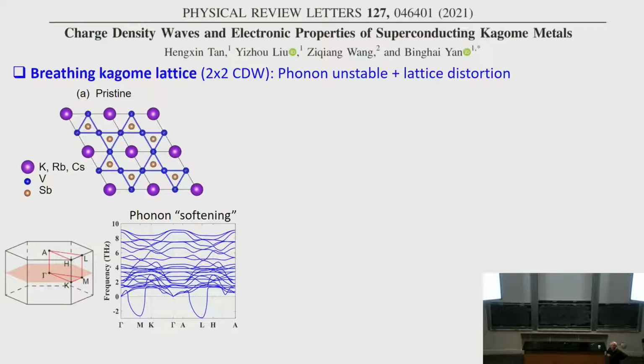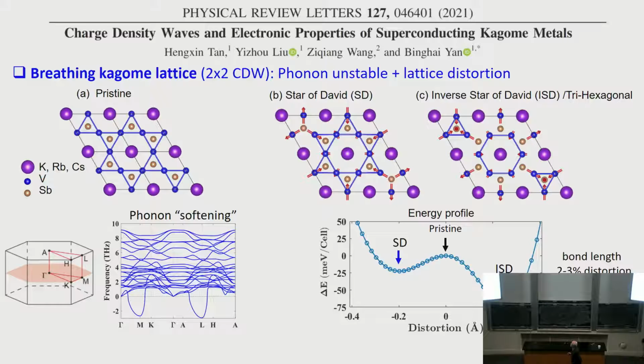Okay, so I'm going into theory. Now, first thing is, can you explain the CDW? Turns out it's very easy. The Kagome lattice is really not a very stable structure. So the pristine Kagome lattice is never stable, because if you calculate the phonon spectrum of this lattice, you see negative frequencies at the zone boundary, M and L points. So the phonons are not stable, right? The structure is not stable. And these zone boundary modes correspond to breathing of the lattice. It wants to breathe, either in or out. And there are two modes.